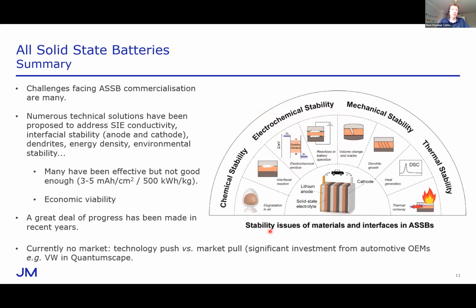And we've addressed all sorts of things, from ionic conductivity to interfacial stability, the issue of dendrites, energy density, and everything has been looked at, and so much has been done. But not many, whilst they've been very effective, not many have resulted in systems with current densities in the region of 3 to 5 milliamp hours per centimeter squared, and energy densities in around 500 watt-hours per kilogram. So there are significant challenges ahead still.